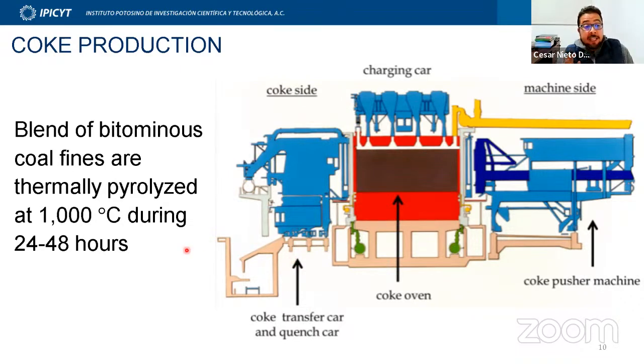Now, the production of coke has very high energy consumption. It depends on the company that is making coke, but it has to elevate the temperature of the oven to around 1000 Celsius, and that takes from 24 to 48 hours to have one batch of coke. And obviously you release a lot of energy, and also you release a lot of air pollutants.